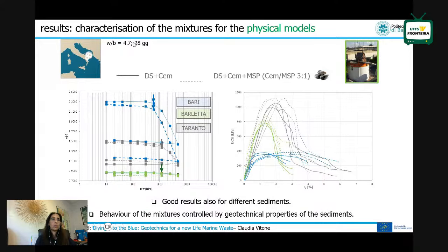If we look at some results, if we fix the water-to-binder ratio after 28 days, the oedometer test of different sediments from different port sites, you can see here that the dashed lines mean the solutions with the shell powder. These continuous lines mean the solutions without shell powder, so the control solution. Again, you see that there is a very good performance of the solutions including the shell powder. And also during unconfined compression test, we have a peak strength of the dashed lines that is similar, sometimes even higher than that of the continuous lines, the control mixture solutions.